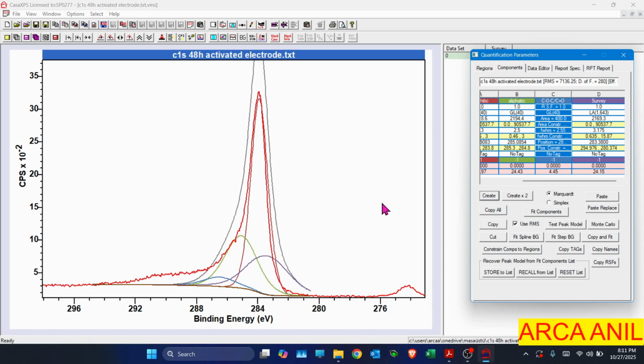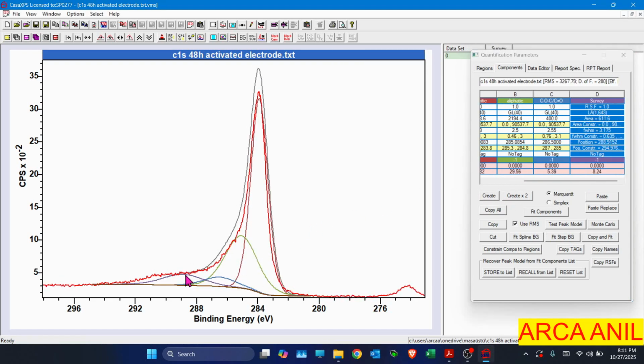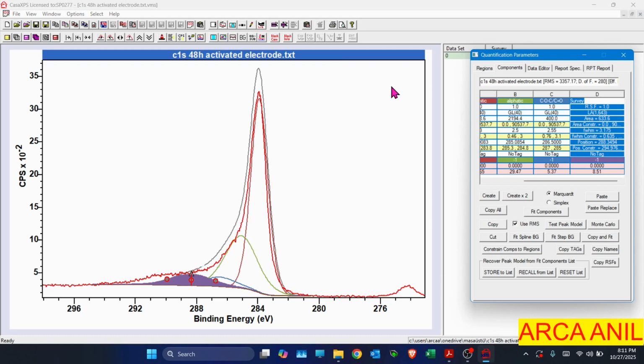Okay, I will put another peak. It should be around here. And this is for the ester groups. For carbon, no, oxygen double bond, carbon, oxygen. So this is our ester group. Again, I will use GL40. And full width half maximum, I think should be less than 3. Or it should be between 0 to 3. And position should be about 288.2.